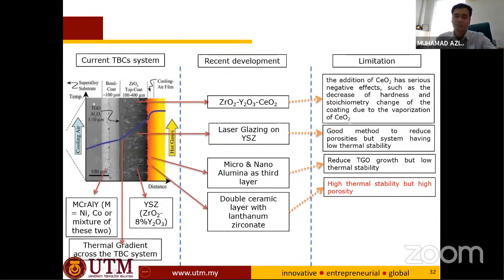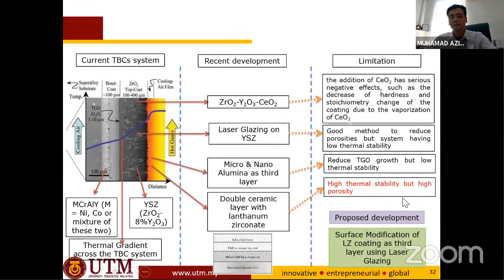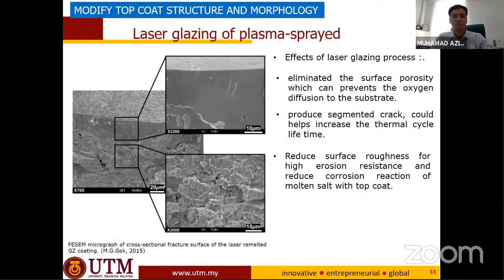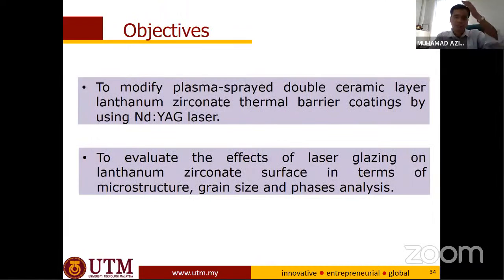This is very good, but because of the problem of porosity, in the current research we propose the development of laser glazing. You glaze or modify the surface. So this is the laser glazing. For example, we can see the structure is more packed. If you have a more packed, denser structure, you can reduce the oxygen diffusion because you seal the surface. So the objective of this research is to modify the plasma sprayed double ceramic layer lanthanum zirconate thermal barrier coating by using a laser. The one that we use here is an Nd:YAG laser to evaluate the effect of the glazing.